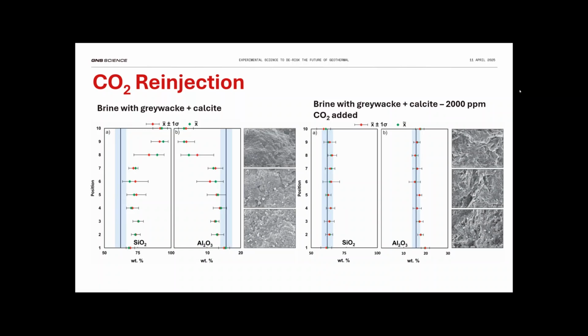This is the exact same rock and brine, but this time we've added 2,000 ppm CO2, and there's no silica scaling. You can see that the green is the mean and the red is the average surface composition of the reactive material. The bars are the 1 standard deviation.